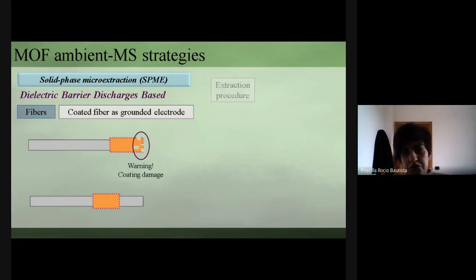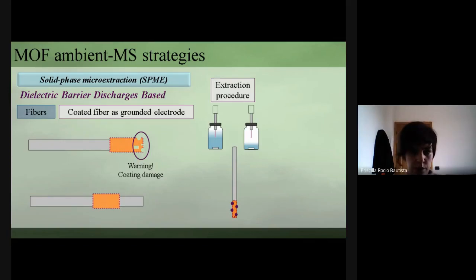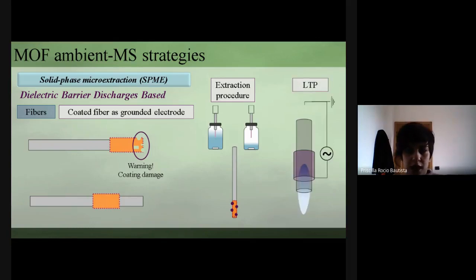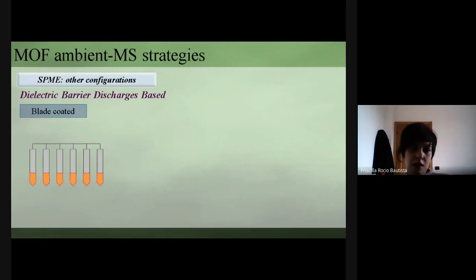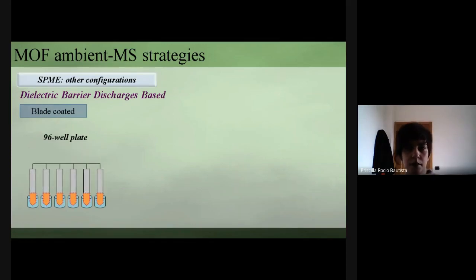The procedure is quite simple. The first step is the extraction in direct immersion or headspace mode, depending on the target analyte. And the second step is to replace the LTP grounded electrode with the coated fiber based on MOF. In this sense, the analytes are ionized in the same plasma device. Well, until now, the presentation was focused on a wire as a support to obtain a fiber based on MOF. However, SPME implies other support configurations such as blades. Coating blades are commonly used in the 96 well plate SPME approach, where up to 96 samples can be analyzed at the same time.